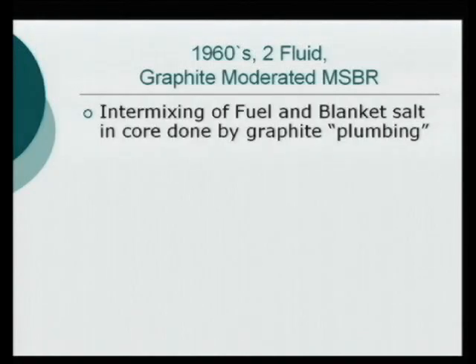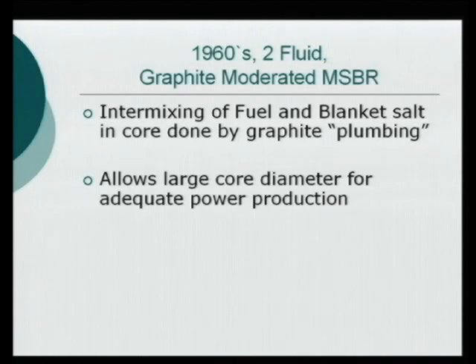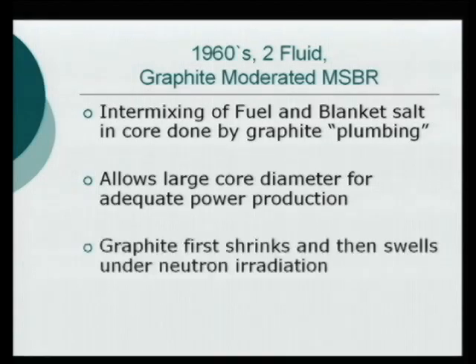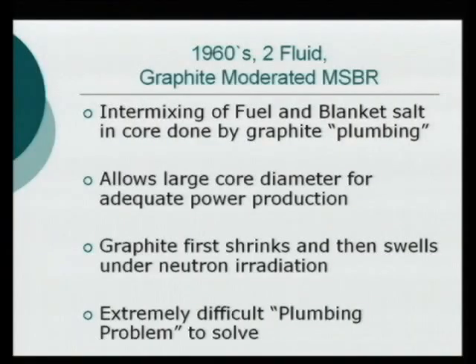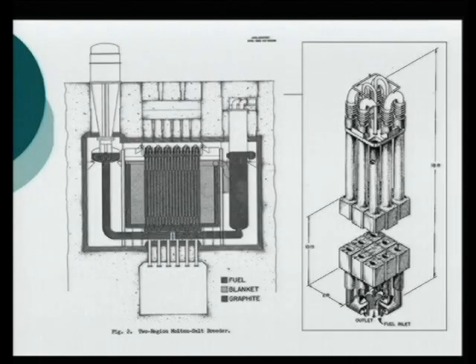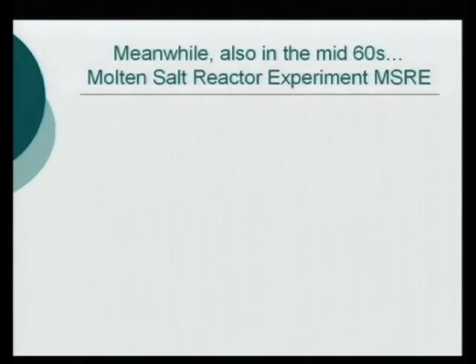Now, that intermixing of fuel and blanket salts done by graphite plumbing does give you the ability to have large core diameters and adequate power production, but that graphite, when it's under neutron radiation, first shrinks a little bit and then starts expanding. And that's changing the ratio of the blanket salt and the fuel salt. It's just giving all kinds of problems. And that plumbing was so complicated as well, any sort of one crack would basically mean replacing the whole core. Very hard problem. This just quickly shows some of the engineering specs. Fuel salt moving up and down a tube here, and blanket salt sort of getting in between the cracks of these tubes. Very difficult.